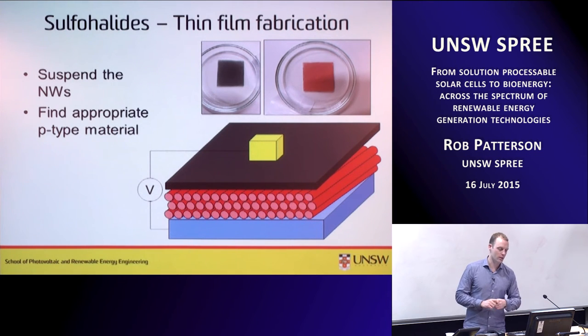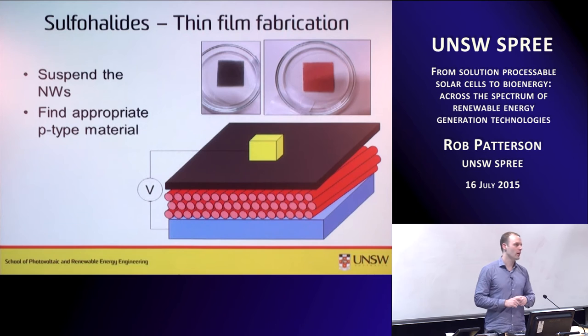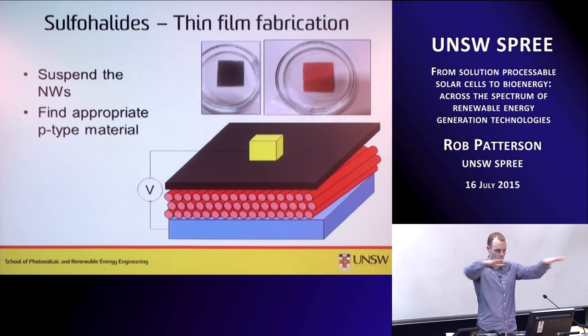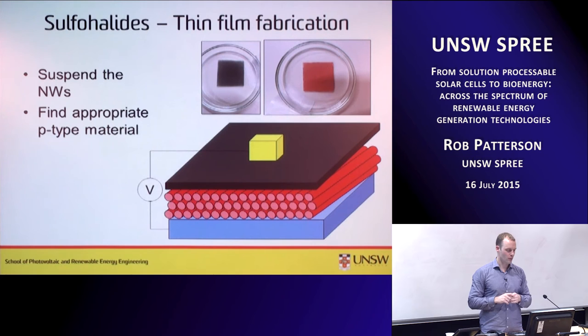I'm probably going to have to find a way to suspend the nanoparticles a little bit better. In our nanomaterial thin films, the nanoparticle solar cells that we make, the colloids are extremely stable. The suspension is beautiful, and there's no settling. In this case, the agglomeration is quite substantial, so we end up with these big blobs going down on the surface rather than a nice even coating everywhere.